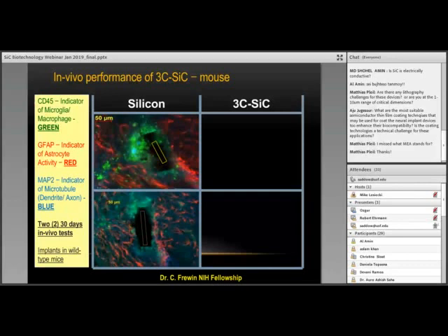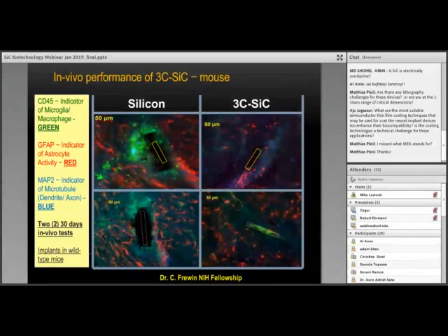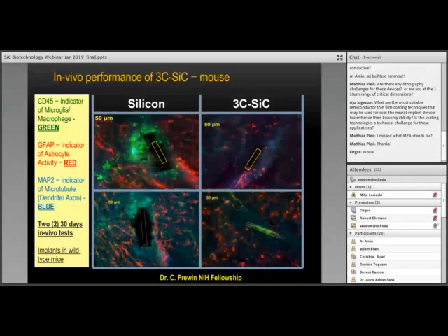This is all tissue histology, for those of you familiar with that, with multicolored staining. Here we see where it was really hard to even know where the implant was in the top image. In the bottom image, a piece of the silicon carbide probe remained intact. And cubic silicon carbide fluoresces in the green. So what you're seeing there was very nice actually, quite fortuitous. We're able to actually see neurons in blue intimately connected to the probe after 1 month in the mouse's brain. Quite exciting stuff. So again, the challenge is now to translate this materials result to a device result.